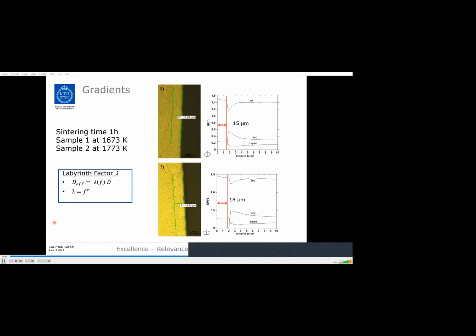Here is shown the result of the Dictra simulations. And on this side, we have the number of moles of the different phases as a function of distance from the surface. And here is the experimentally observed gradient zone. You can see it here. And this is a cubic carbonitride phase. There is a maximum here, and then it goes down to 0, and you have the gradient zone. And here is for some other conditions, and you can see that there is a reasonable agreement.